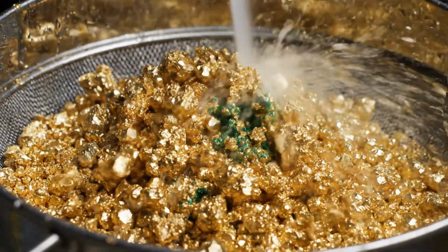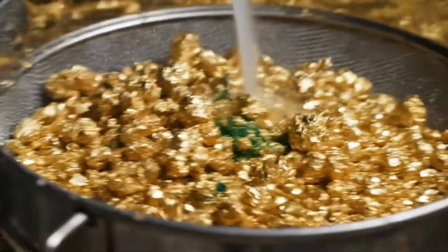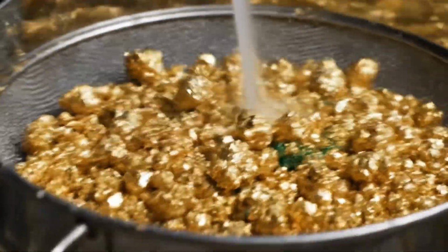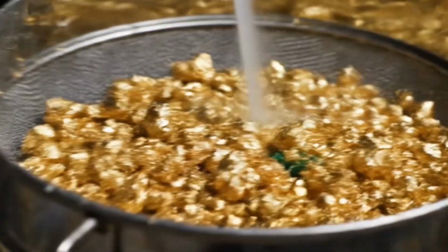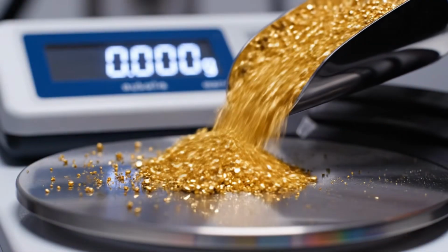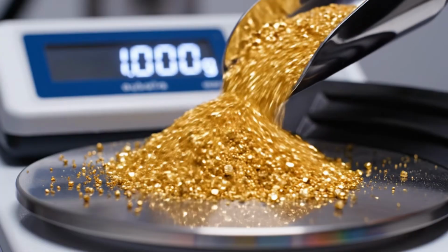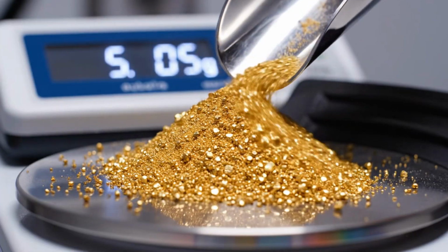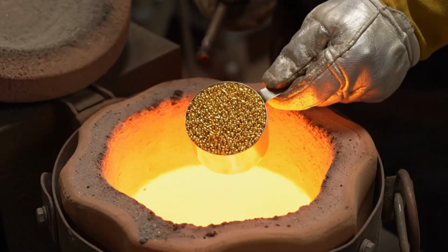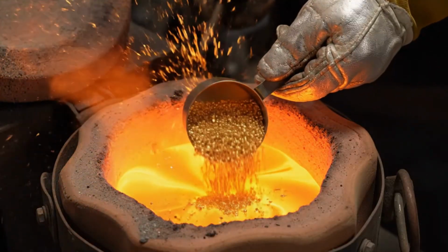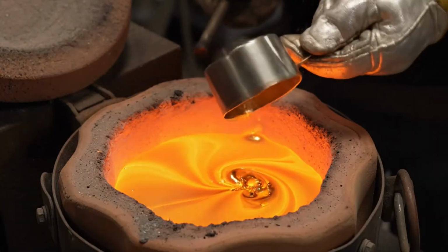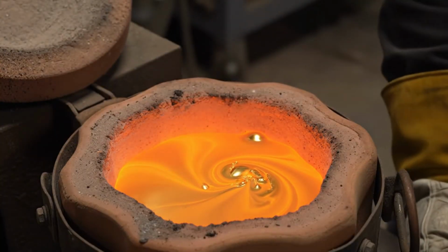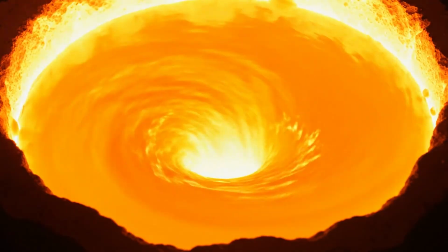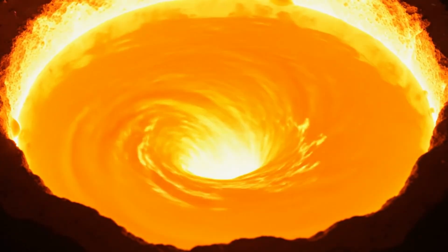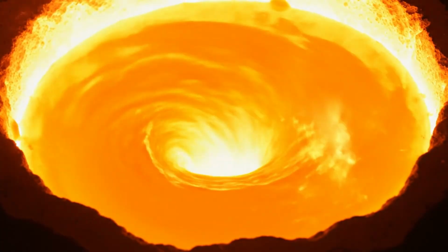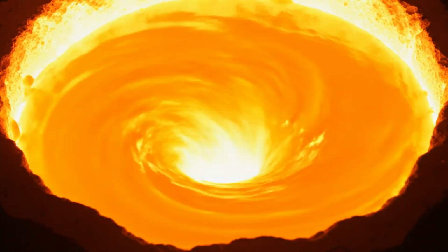We wash these crystals thoroughly to remove any lingering acid, ensuring that nothing contaminates the final melt of this precious and refined material. The clean grain is dried and weighed with obsession, as every single gram represents a significant amount of current market value and effort. Now begins the final casting, where the pure grain is introduced to the induction furnace to become the iconic bars we all recognize. The induction coil generates a magnetic field, heating the gold instantly without direct contact, preserving its absolute purity throughout the critical melting phase.